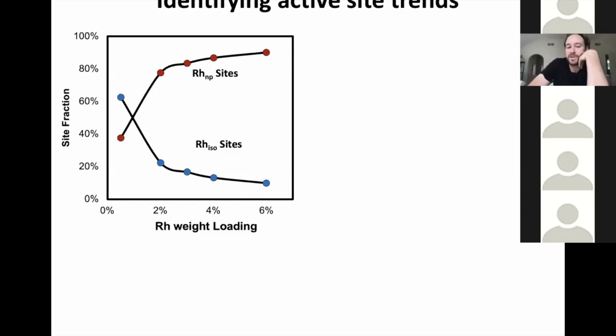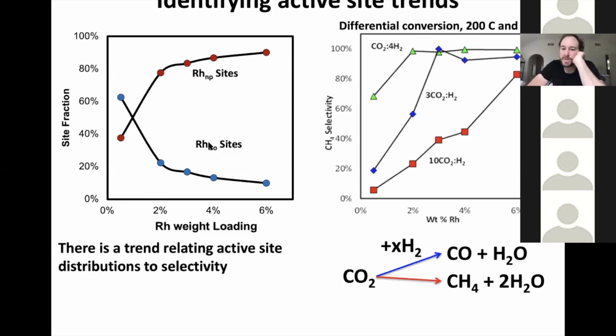So we've made this series of materials, and we quantified the fraction of sites existing in each type of local environment, either on nanoparticles or isolated sites. Let's see if we can correlate this to their reactivity. When we measure selectivity here, with CO2 going to either CO or methane, you can see that as we increased rhodium loading, we always saw higher and higher selectivity to methane. This is consistent with the idea that methane formation happens over these rhodium nanoparticle sites.